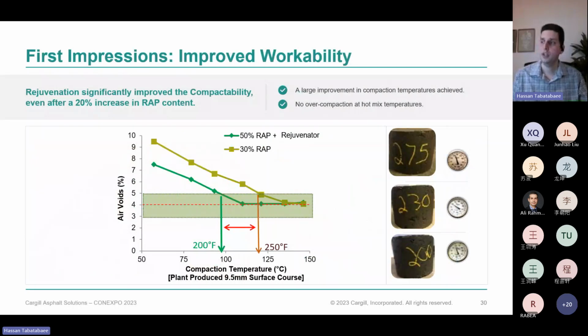As I mentioned, a lot of time, one of the first things that you will see with the recycling agent is a reduction in temperature and improvement in workability and compaction with higher RAP. As you can see very clearly here, with a reduction of temperature, you're not only maintaining compactability, but you're improving it, which is significant when you're going from 30% to 50% RAP.